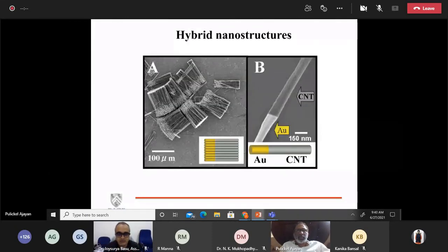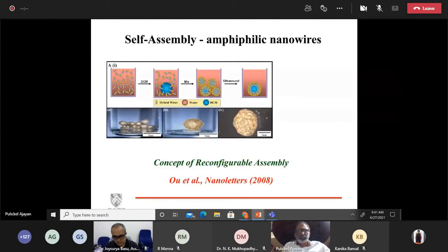For example, you can create very controlled hybrid nanostructures using a templating process. This is something that we did quite a few years ago. We were able to create these beautiful nanowires with metal and carbon. And obviously, because they have different chemical properties, these types of hybrid structures are almost amphiphilic. So in this particular case, gold can be hydrophilic and carbon can be hydrophobic. So even from a very simple perspective, such hybrid structures can be multifunctional.